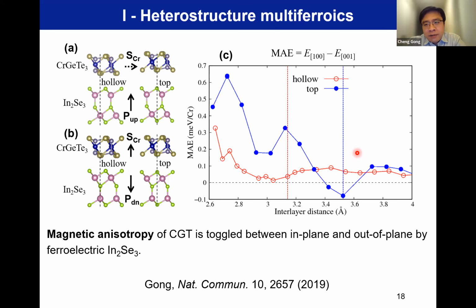So I borrowed the concept from the multiferroic community. If we have such a heterostructure multiferroic like 2D CGT, a ferromagnet, and 2D indium selenide, a 2D ferroelectric, you can put them together. Then this ferroelectric will allow you to use a small voltage to flip the ferropolarization. Ferropolarization flipping means the ions are moving. Once the ions are moved, that means the interfacial crystal field can potentially be largely altered. So it's not only an electric field or an electronic injection, but there is an ionic bonding alteration.